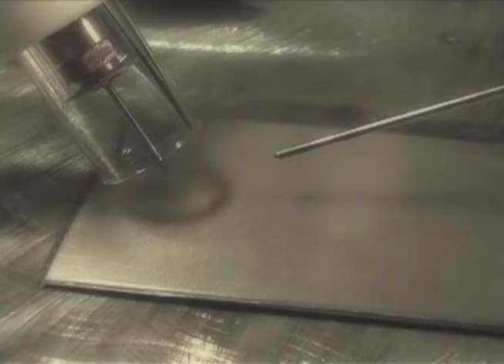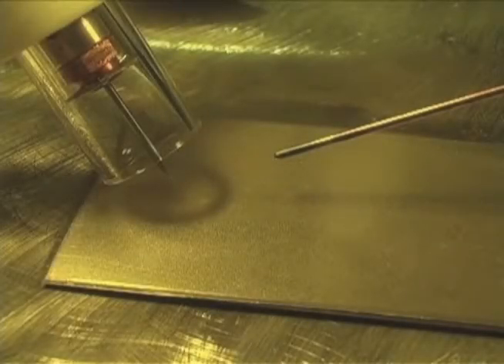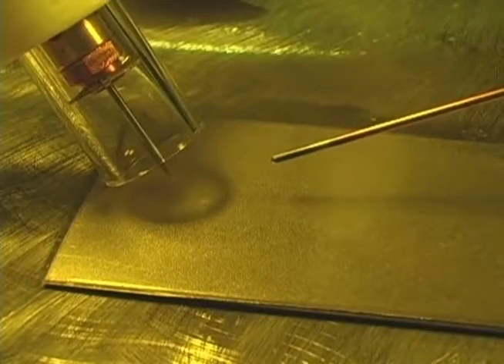Again, the key is in the puddle. You have to operate the foot pedal and control your torch so you can keep the bead width consistent. We establish the arc and gradually push down on the foot pedal to increase the amperage to start a molten puddle. When we have a molten puddle about 3/16 of an inch in diameter, start to add the filler metal to the leading edge of the puddle.